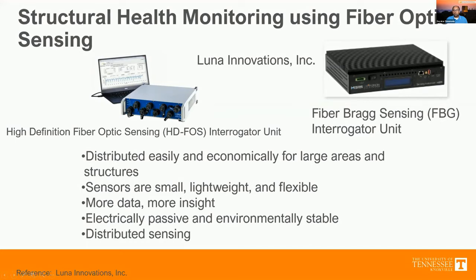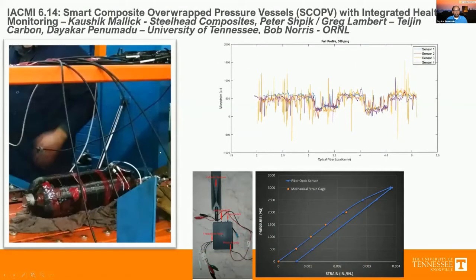Here we can measure strain at predetermined locations, and you can have the gratings etched as needed at given locations, and they respond to applications as high as 5 kilohertz. So for dynamic applications, you use fiber Bragg gratings. For most of the normal applications, we would be okay with high definition fiber optic sensing. So I want to quickly introduce to you the 2 applications. This technology we have developed essentially to monitor pressure vessels.